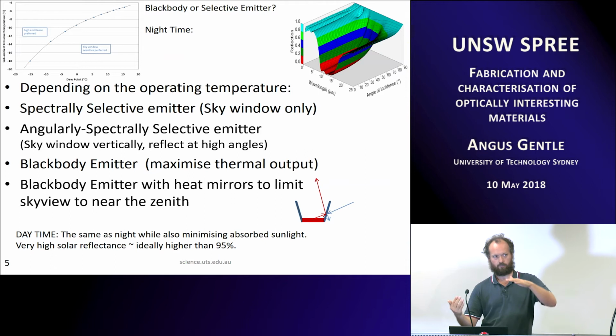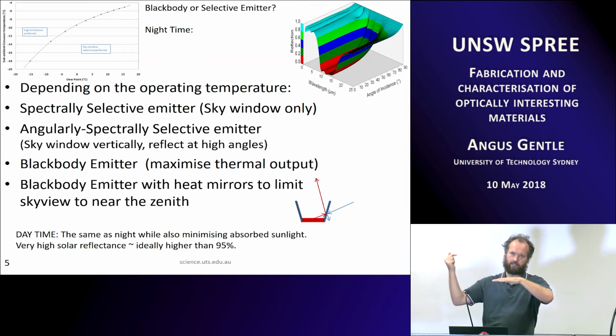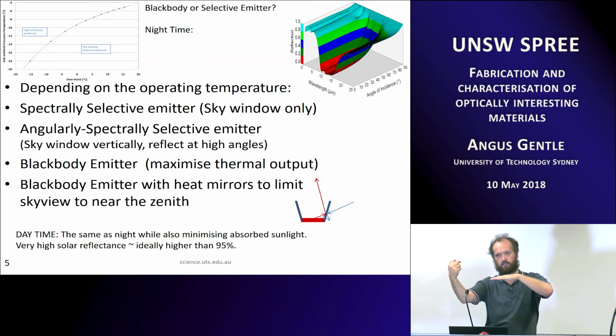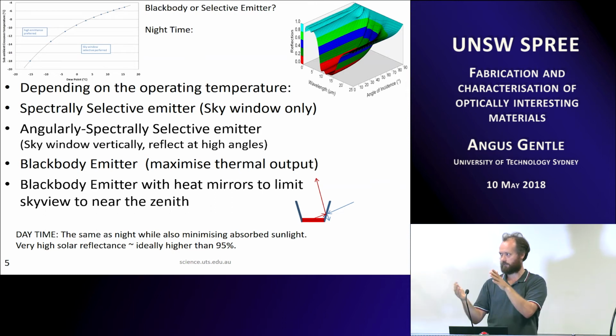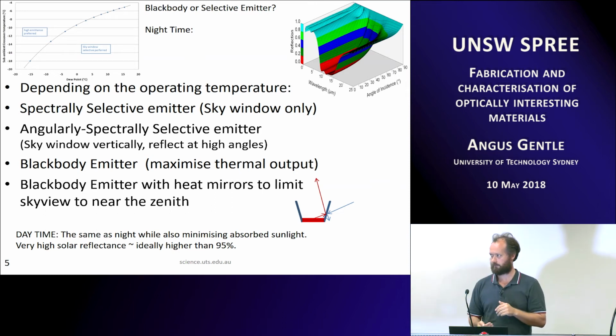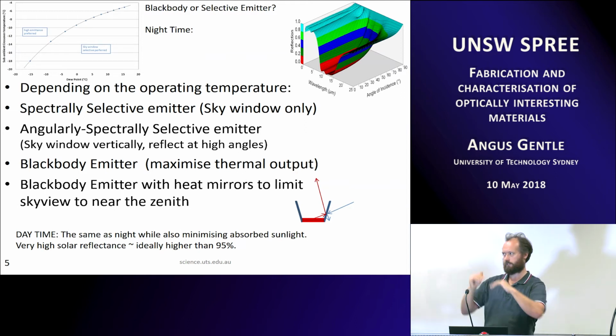But if you look at where the sun is during the day, even if you've got, say, something 85% solar reflecting, because it depends on how much is being absorbed, when the sun drops to the lower angle, then you can actually be cooler than ambient quite a bit of the day, even if it's not a really, really high reflectance. But in the middle of the summer, you'll still get the peak because you start to get the 1,000 watts coming in. And this also depends on which direction your roof is.